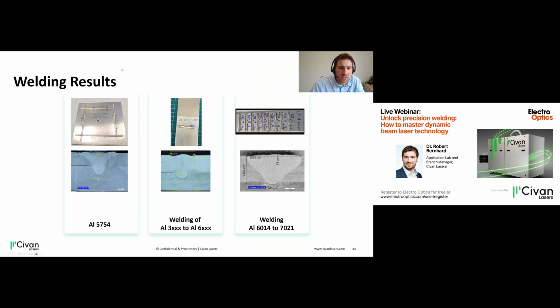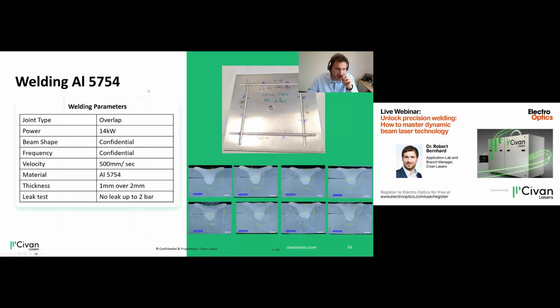So the welding results in this regard: aluminium, as well as welding 3000 series to 6000 series, as well as 6000 to 7000 series. And what you can see here, and I want to give an example on the left aluminium in a moment, is that our laser is welding these with very nice cross sections, but also very fast. So here we are talking about the welding of aluminium 5754, and we are reaching up to 500 millimeters per second. And while being this fast, we have these coupons that are leak-free at 2 bars.